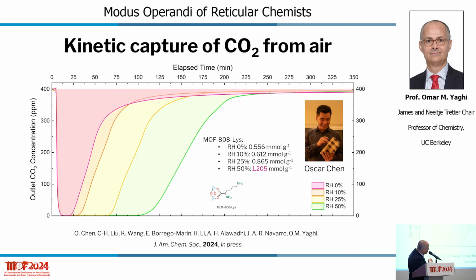Okay, 400 ppm of CO2, it drops to zero. It takes up that CO2 and stays in the pores until the pores are completely saturated before it breaks through. And look at higher humidity, the uptake is even more. Okay, in this case, it's not glycine, but it's lysine because it's more basic. The capacity is quite nice.